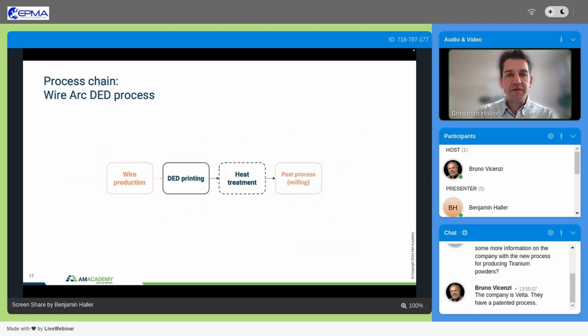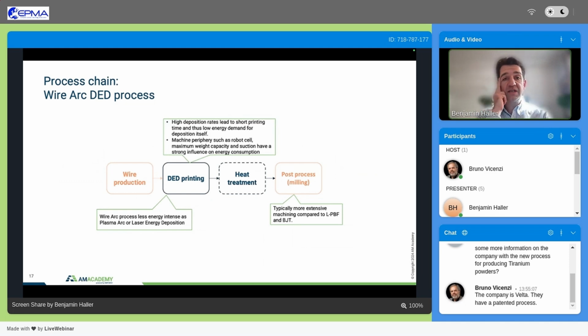And then third, a more simple process chain is the DED process, here the wire arc. Here the printing itself, because it is a relatively fast process, has actually not such a high demand for the deposition itself. What is sometimes more important than the deposition is actually all the periphery around the printing: the robot cell, the weight capacity, the suction of the process. This can have a relatively high energy consumption. And then exactly the energy source used. Here, electric arc has a relatively low impact, plasma more, and then laser would have a higher CO2 impact.